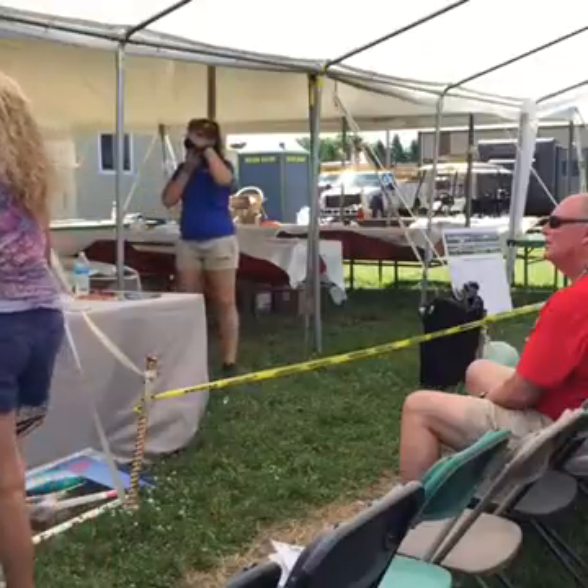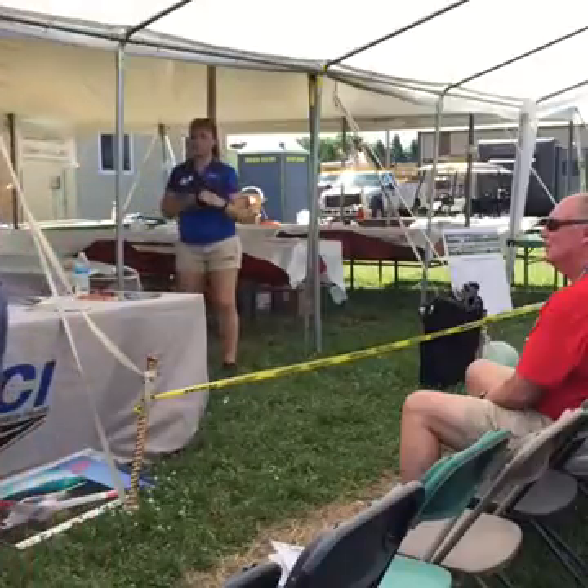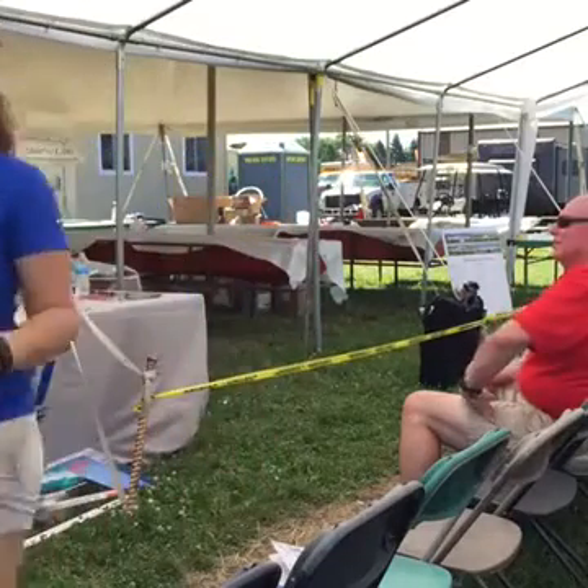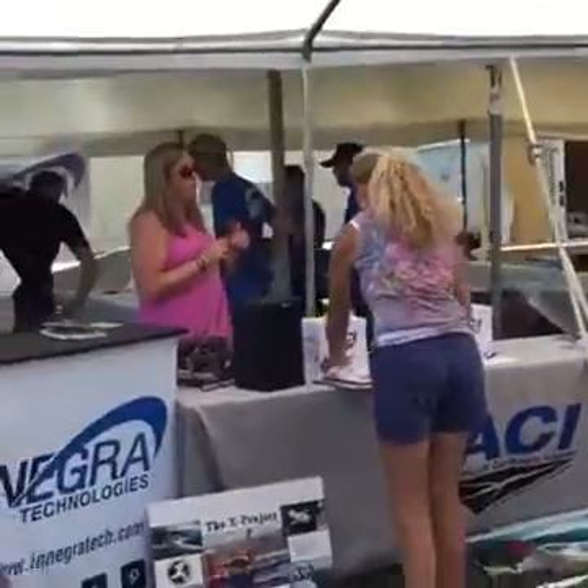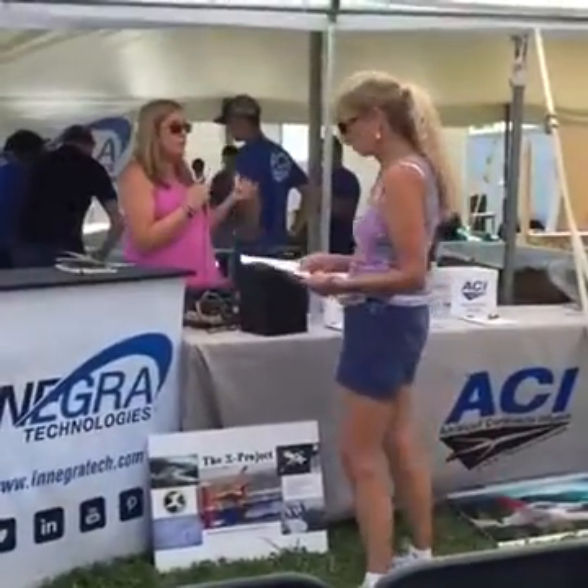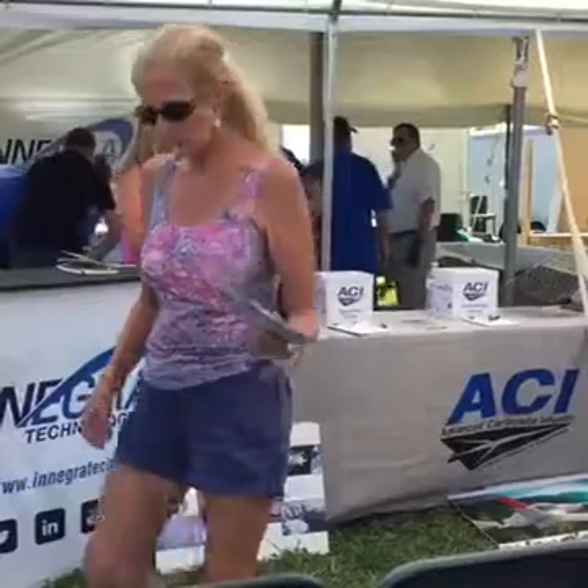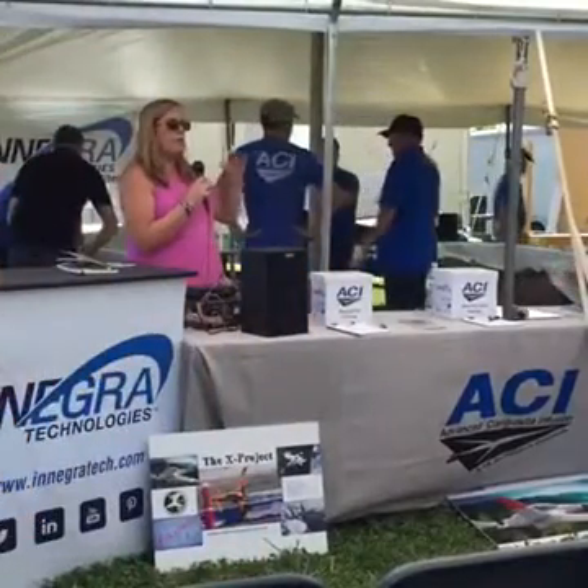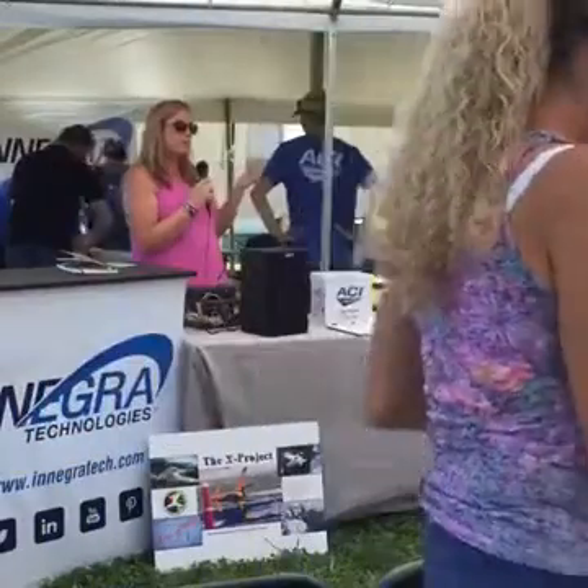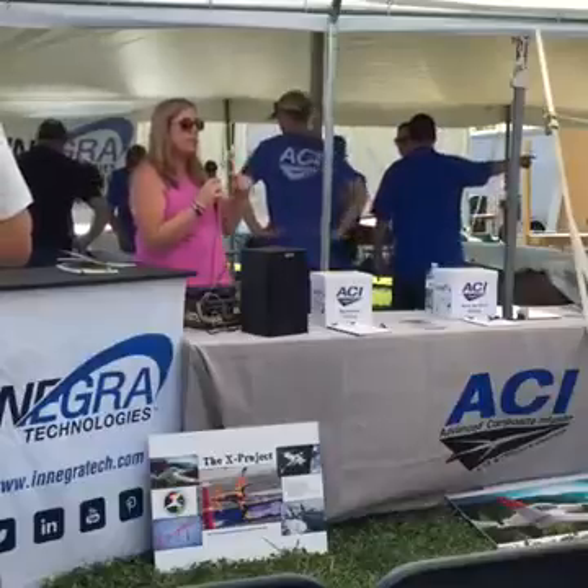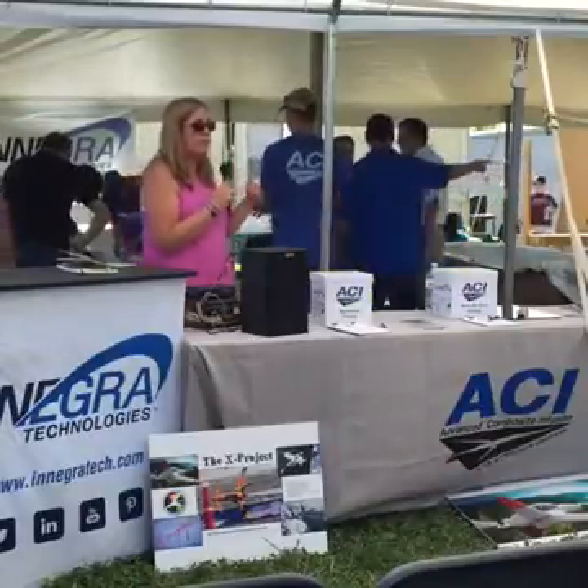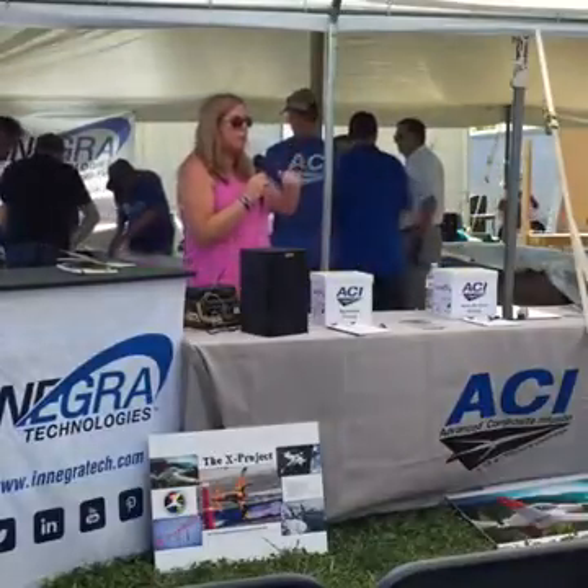Aaron, and I'm with TechStream. TechStream is a carbon fabric made by taking the tows, as Russ explained, and then we spread those tows into a very thin tape, and then weave those tapes into a fabric. And so the resulting fabric is much thinner and stronger because you don't introduce fiber crimp into the carbon fibers like you do in a typical fabric going up and over the tows.